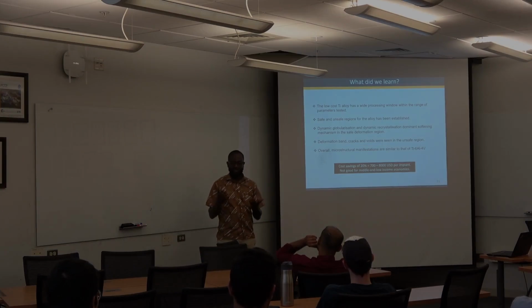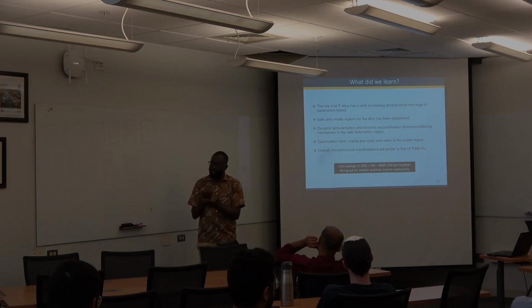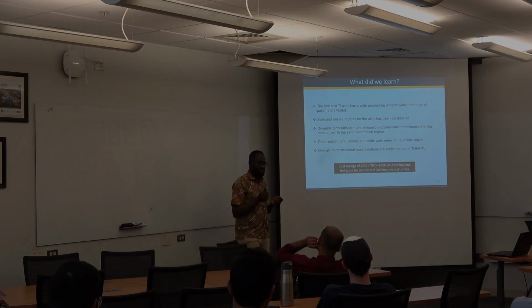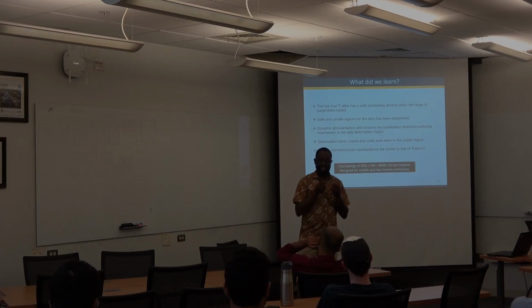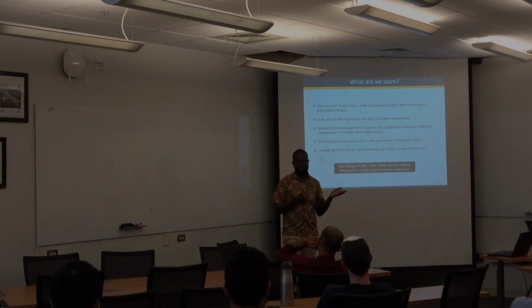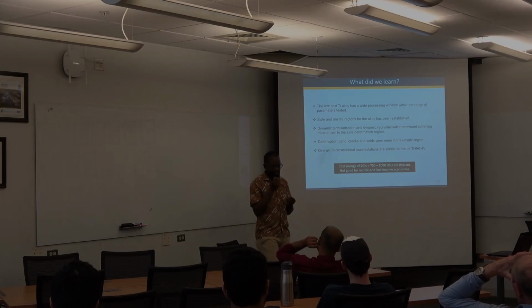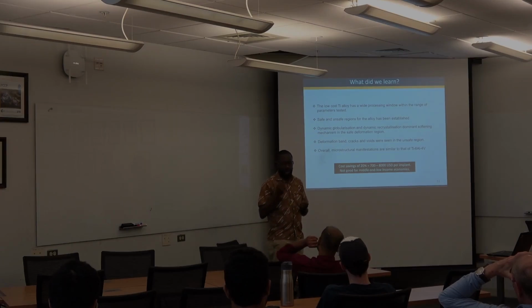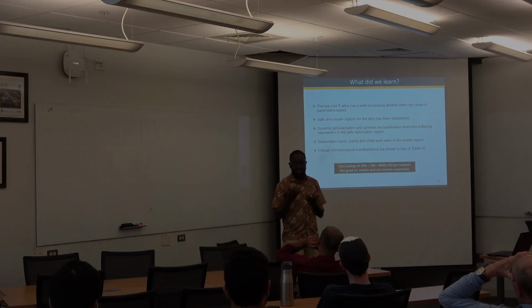But one thing that I bring here today is to see if it's possible for us to answer this critical question: what is iron doing to titanium that is helping it to reduce the corrosion rate? Because most of the argument is that iron has poor corrosion resistance. So why is it that when we add it to titanium, it does reduce the corrosion rate? We know that titanium's corrosion resistance is from the surface that forms titanium oxide, that passive film. Right? And this film changes as you introduce different alloying elements. But we don't have the capacity to characterize that to see what's really going on.